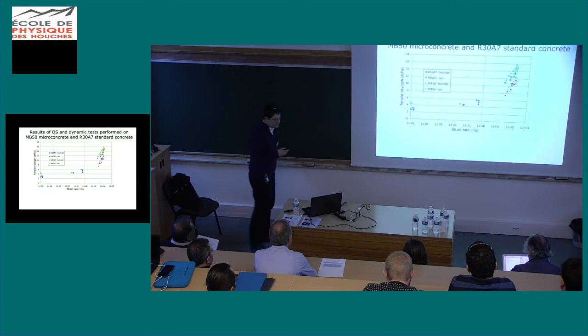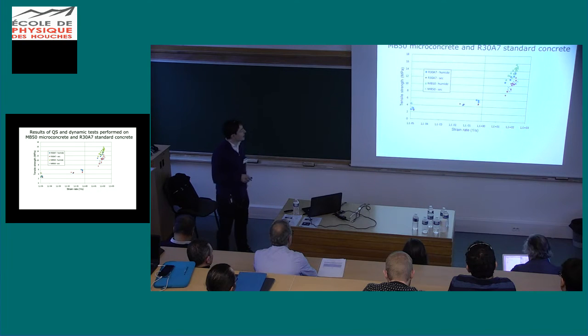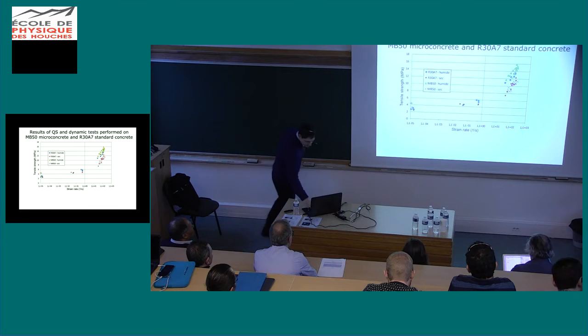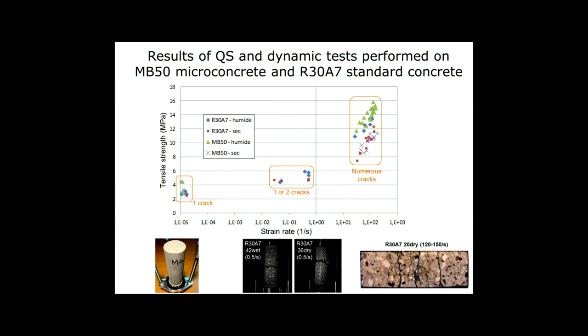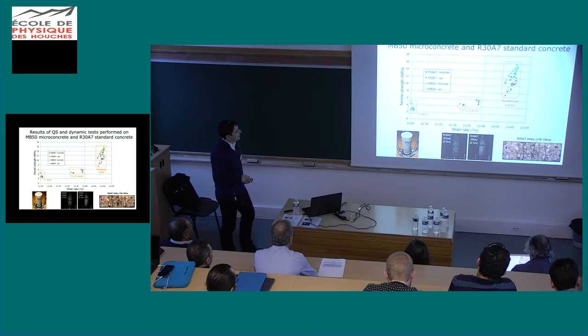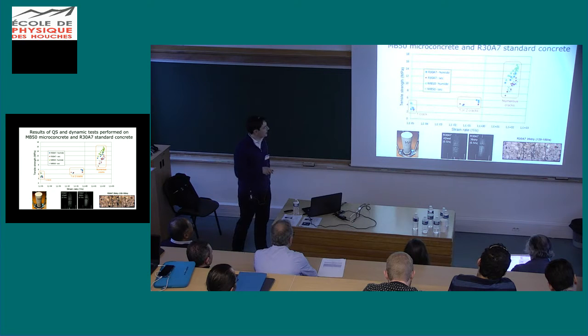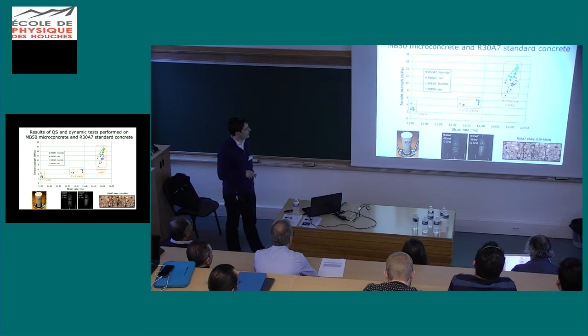Okay, so, but what is important here are the results. And the results show that in quasi-static, the failure stress is about 4 megapascal. At intermediate strain rate above 1 second minus 1, we have just a little increase of strength, from 4 to 5, 6 megapascal. Whereas above a certain strain rate, we have a sharp increase of strength.